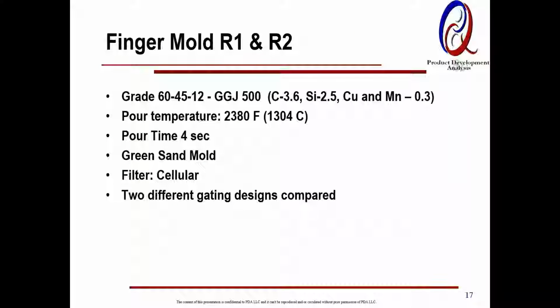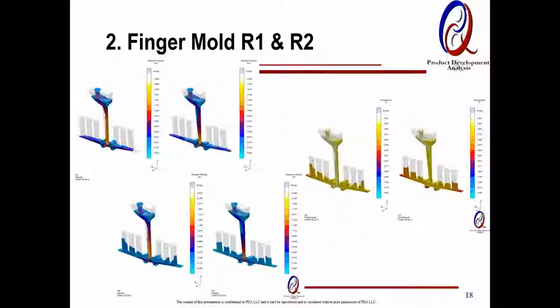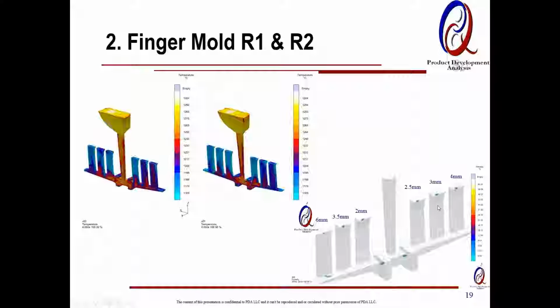Years of work has been done in this area just to measure the fluidity and compare between alloy A and B type. So what we did is we kept in the simulation as well as in the experimental conditions all the process parameters, such as pour temperature, time, the type of the mold material, the applied vent and so on. And we got a feel for this particular alloy that we got higher fluid distance. This is the one way we measure, the overall length or the maximum dimensions. Here we got like 21.5-inch versus 17-inch, the commercial alloy. And we were able to simulate, get a feel for it before we actually ended up making the prototype castings and plate castings.